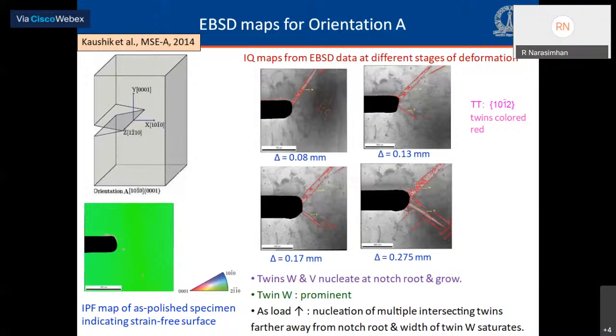So if you take a look at the sequence of images, very early during the deformation, 2 twins W and V nucleate at the notch root, and with increasing deformation, they both widen as well as extend. However, as the deformation proceeds, you can see at the bottom right side image, multiple intersecting twins have nucleated, and some of these obstruct the extension of the initial twins. So the width of the initial twins increases and then saturates at around 120 to 140 microns.